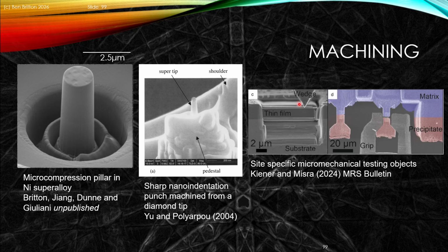We can also use other mechanical geometries. So this is a cantilever where we have a thin film and we use a wedge to deflect and bend that cantilever object. Or we can do effectively a micro-tensile specimen where we can pull apart a tensile specimen by having a fibbed gripper and the surface of the material with the tensile specimen cut into it.